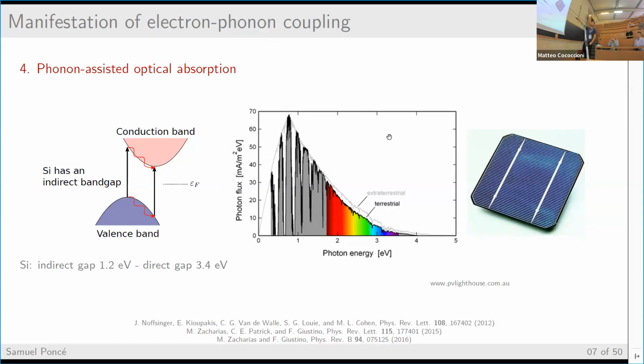But actually, through the interaction between the photon and phonon, if you have both interactions, then you're able to do an indirect band gap transition. So this is called phonon-assisted optical transition. You're using the momentum from the phonon and the energy from the photon in order to make this transition, and therefore you're able to absorb a much larger fraction of the spectra.